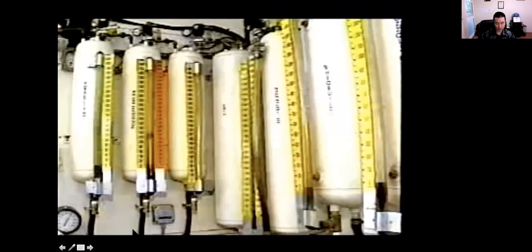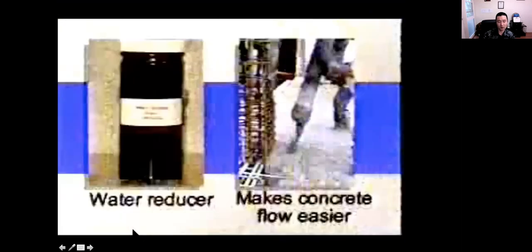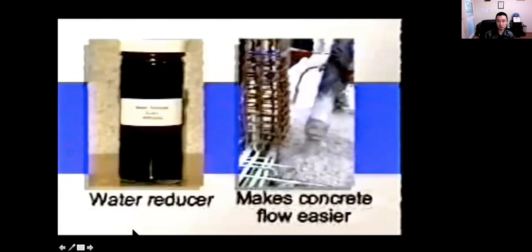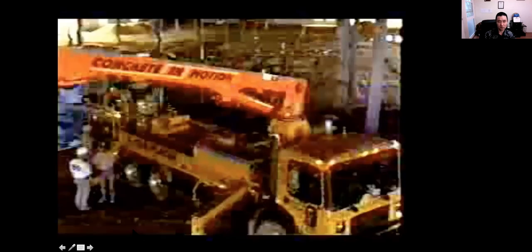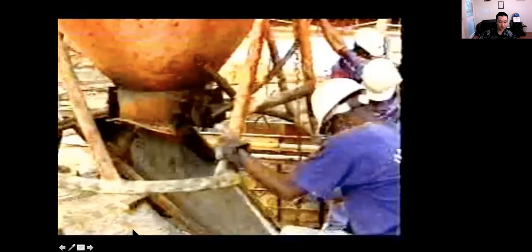Chemical admixtures give concrete properties it normally wouldn't have. To make a mix more fluid, a water reducer can be added. Water reducers make the concrete flow easier from the pump, through the hose, to this elevated slab in this warehouse, without increasing the water content. If a water reducer is not used, pump hoses can become clogged and blocked, delaying the placement of concrete. Water reducers are also used for concrete in areas that are difficult to place, such as around congested reinforcing steel.